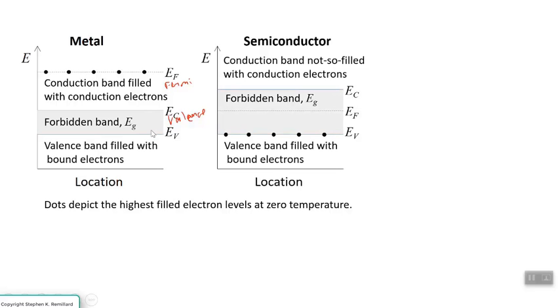which, first of all, has a typical larger band gap. More importantly, there are no electrons residing up here. So what makes a semiconductor a good semiconductor is that the valence band is just perfectly filled. All of the electrons in the material manage to fit at E sub V and lower. There are enough states available to house all of the electrons. And so there aren't any electrons up here on the conduction band.